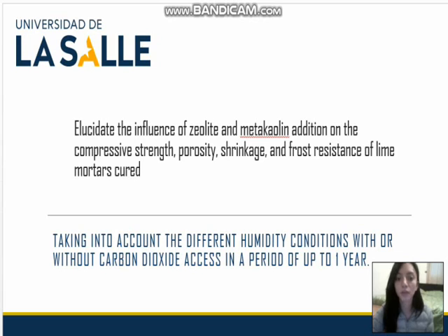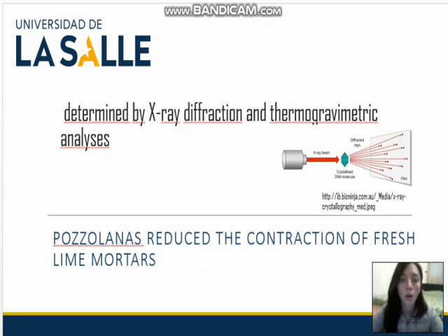This material was tested taking into account different humidity conditions, with or without carbon dioxide access, over a period of up to 1 year, and was determined by X-ray diffraction and thermogravimetric analysis. It was observed that pozzolans reduce the contraction of fresh lime mortars.